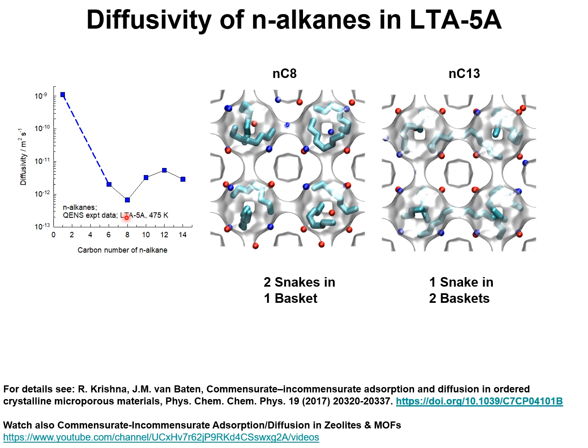The diffusivity for normal octane, NC8, is lower than the diffusivity of tridecane, NC13. To understand the minimum here for NC8, let's look at the computational snapshots showing the conformations of NC8 and NC13 within the cage window structures of LTA5A zeolite.